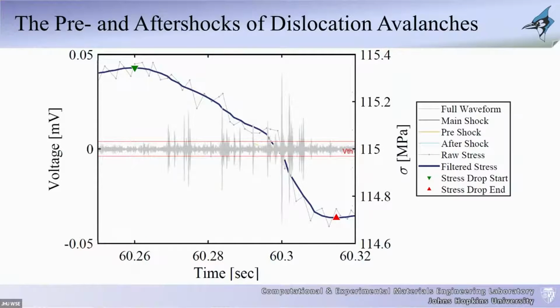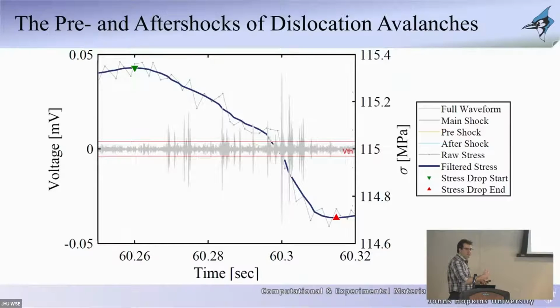Taking this a step further, and learning a lot from what happens in earthquakes, you typically have this idea of pre-shocks that lead to a main event, and then after that main event, you typically have aftershocks. This is really very similar to what we see in metals. So I'm showing you here a single drop. This blue dot and this red dot represent what we define as an avalanche, a single avalanche when the material deforms. So this is a stress drop. And what you're seeing in the background here that is gray and yellow and blue is the acoustic measures that we have. You can quantify and see that the biggest event that happened is this black one here, where before it, there were a bunch of smaller events that led to it. And then after that big event, there were a bunch of smaller events that happened after it. So we can start quantifying this in the sense that these are pre-shocks, these are aftershocks, and this is your